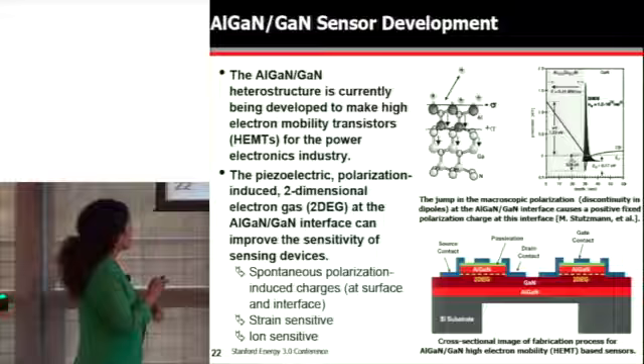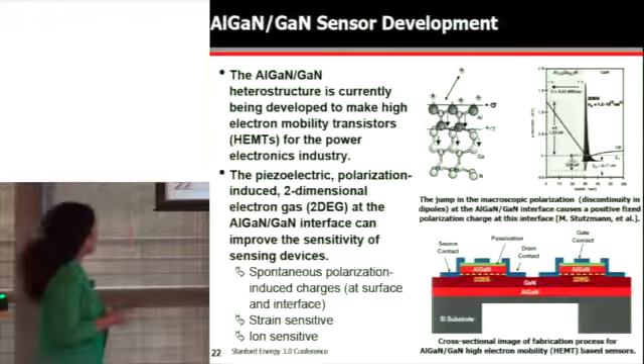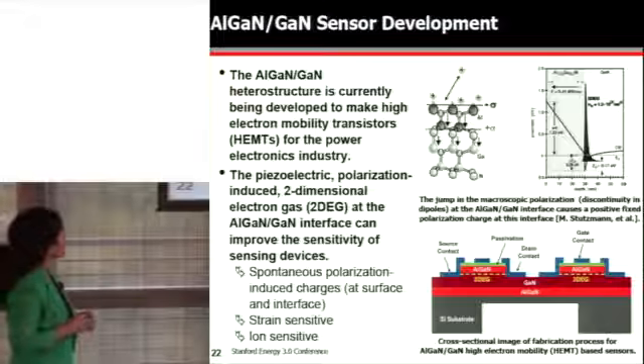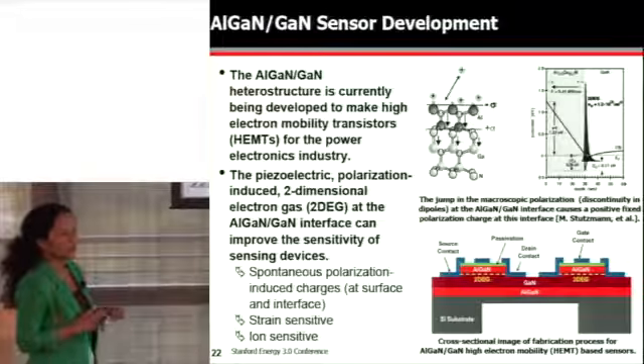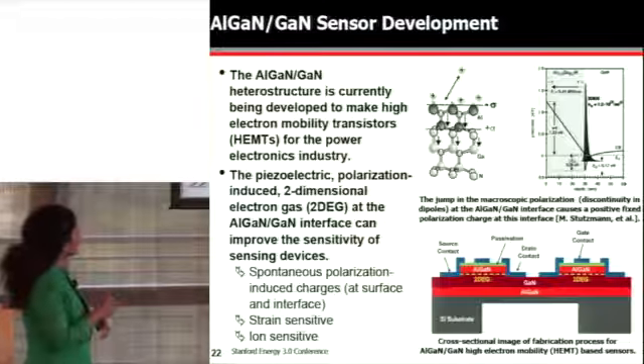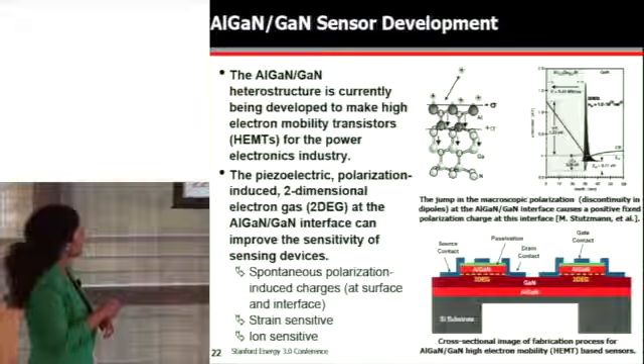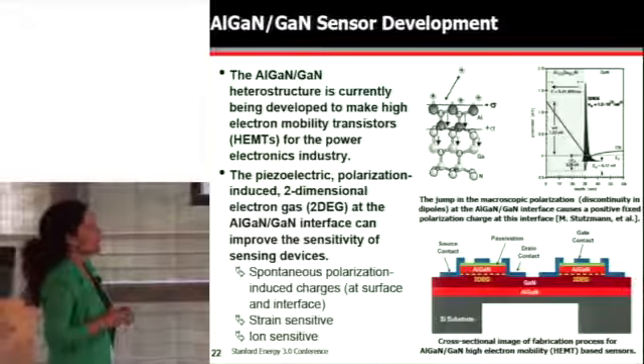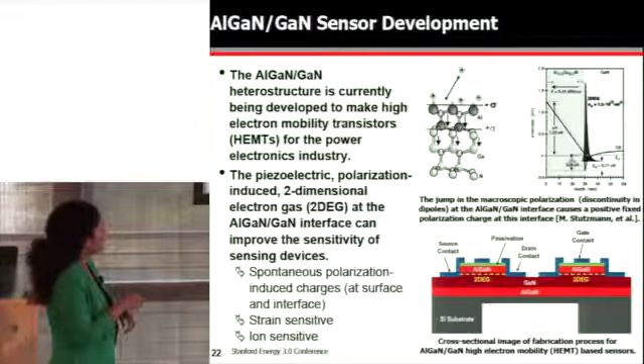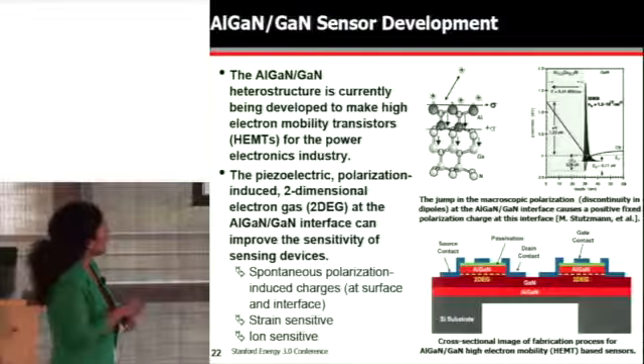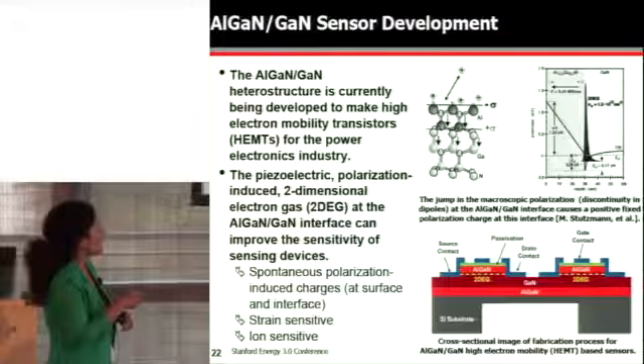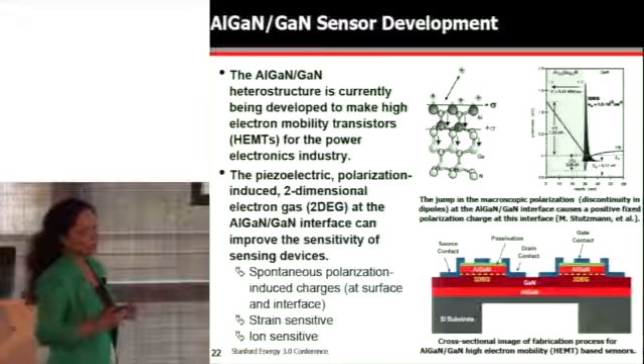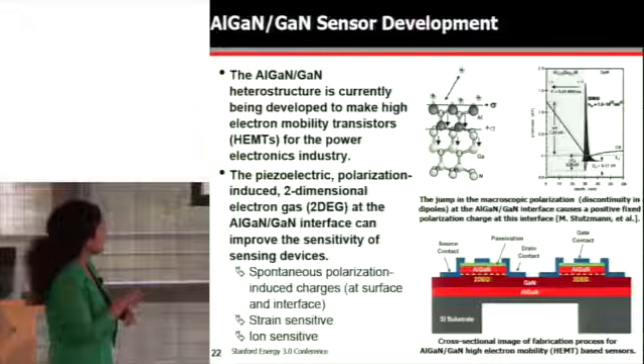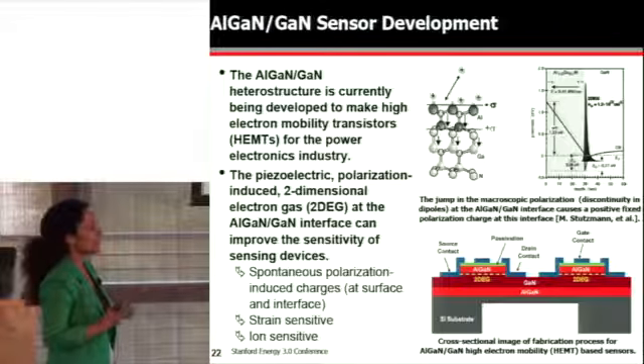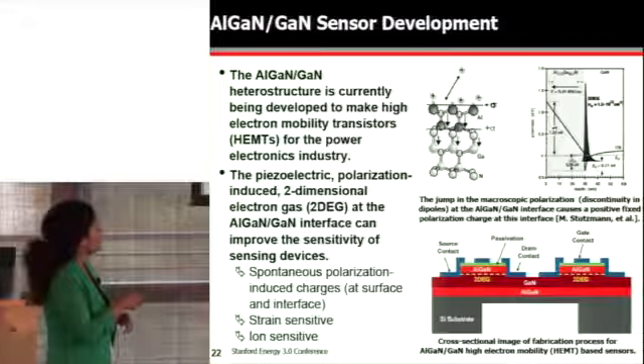Gallium nitride is being explored to create high power electronics, in particular the high electron mobility transistor. And so you create the high electron mobility transistor, or the HEMT, by sandwiching a slightly doped variant of GaN, or AlGaN, on top of the gallium nitride. And that slightly doped variant creates a strain at the interface, and that strain causes a quantum well at that interface, so a high sheet of electrons. People call that the two-dimensional electron gas. And so that two-dimensional electron gas is a way of transporting electrons. So you can actually make transistors out of this material.